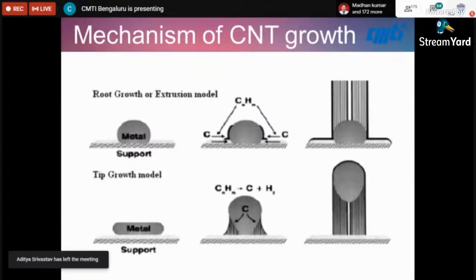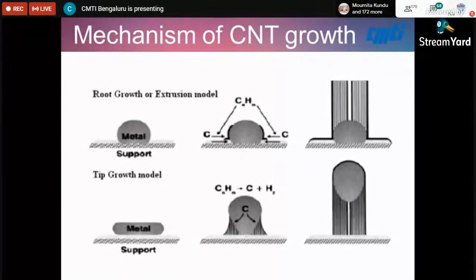So this is a growth model. Let's say you have sprinkled a nanometal powder; it will be three-dimensional in nature, and over that you will start growing the CNTs. Whereas if you have a thin film that is flat, and you put in some sort of carbon gas, it starts pushing the metal to the top and it forms the cap. That is the tip growth model. The metal moves up, and from there the carbon nanotube starts growing from top to bottom.